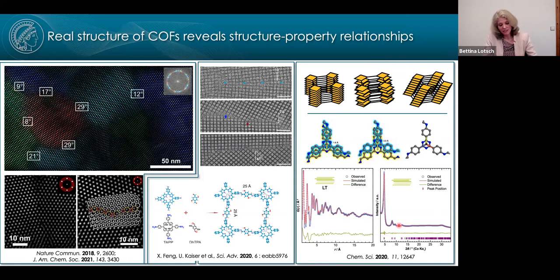And this actually tells us that although these COFs seem to have a very high symmetry structure, from the powder XRD you get very little information. You just see a high symmetry, in that case, hexagonal structure. But when you look closely at the local structure, you'll find that the COFs are much more disordered. And what that basically means, that is sketched here, is that the layers show random translational layer offsets. And so on average, these COFs appear as eclipsed stacked and high symmetry. But locally they are much more disordered and lower symmetry. And that, of course, has an influence on the effective pore size, for example. And that, again, is relevant for catalysis. So I just want to sensitize you for these real structure effects that are important to understand in these systems. And that is actually one of the lines of research we're currently pursuing.